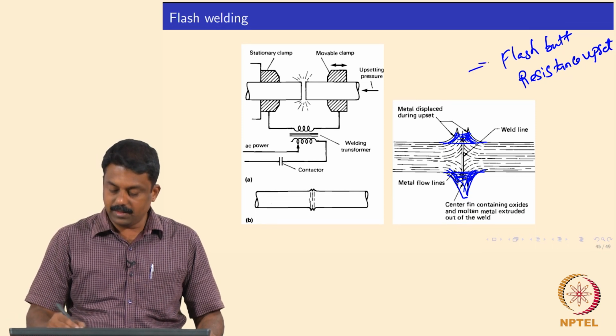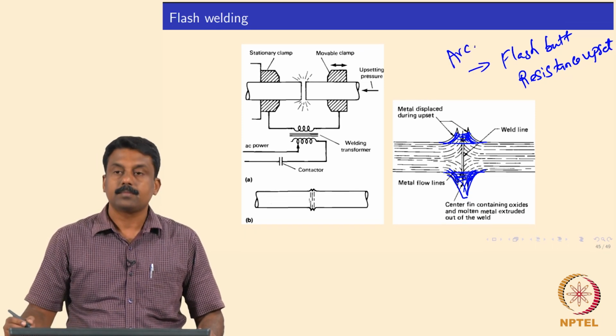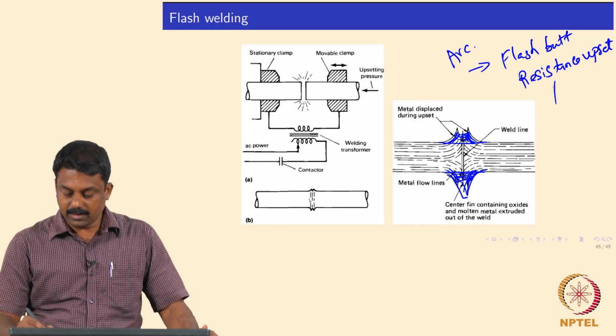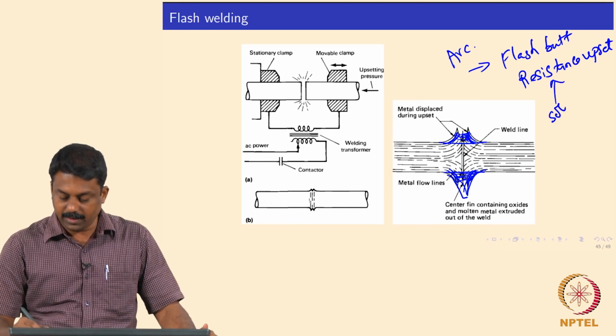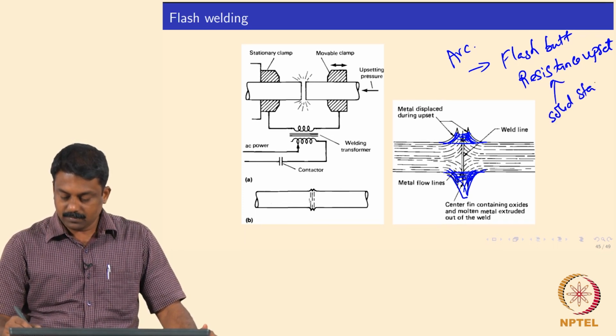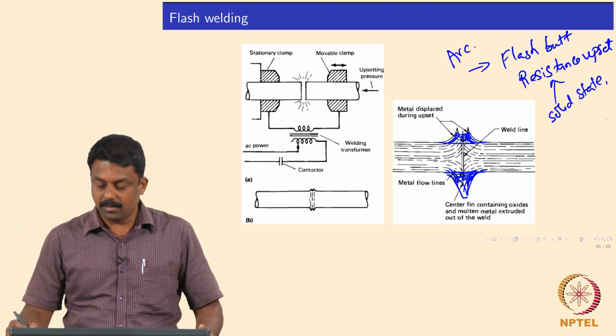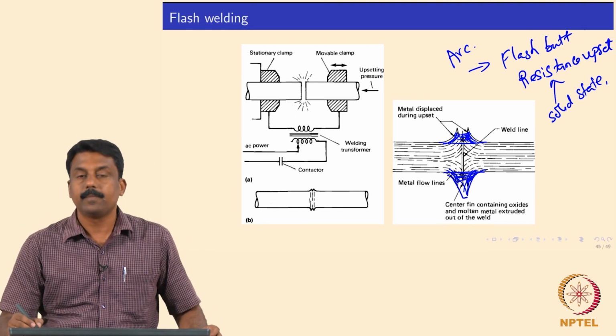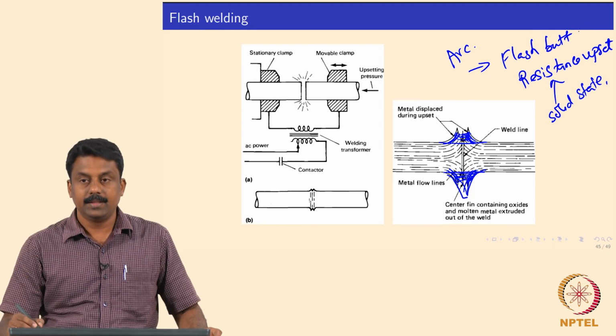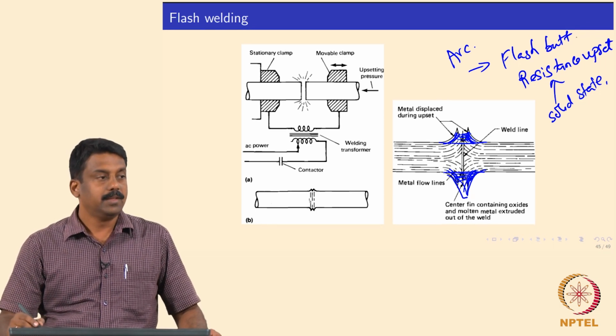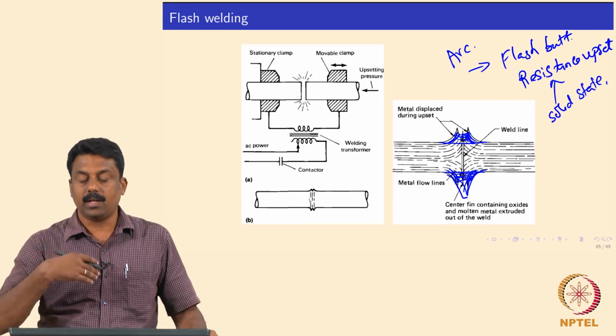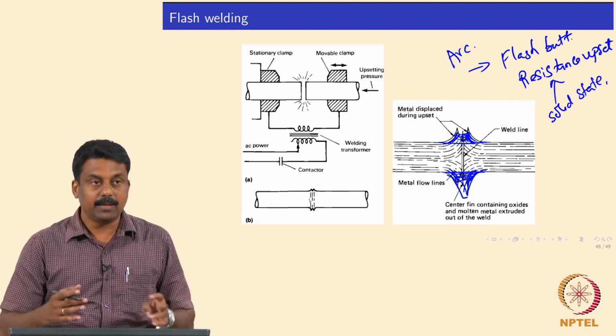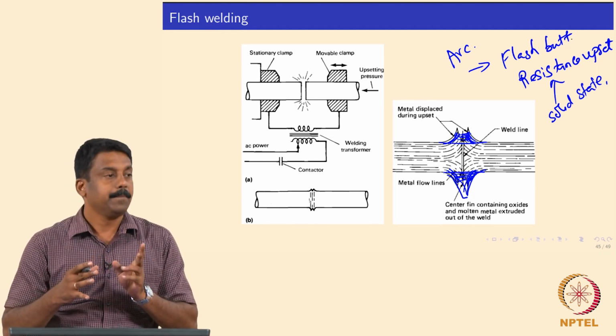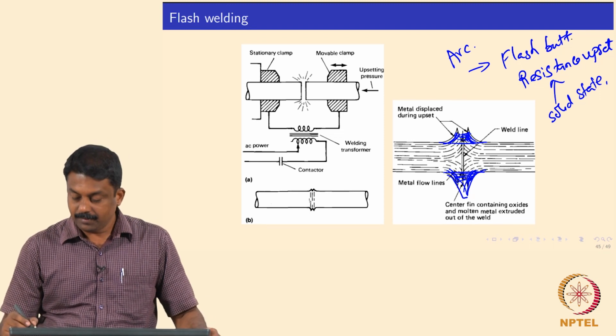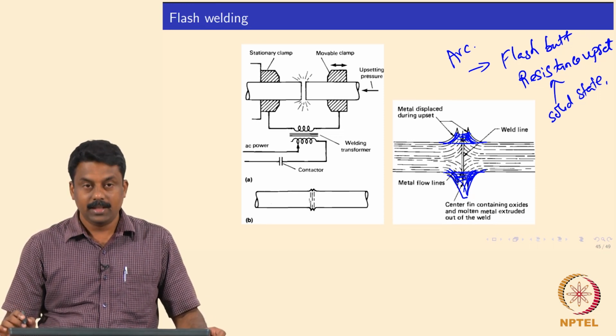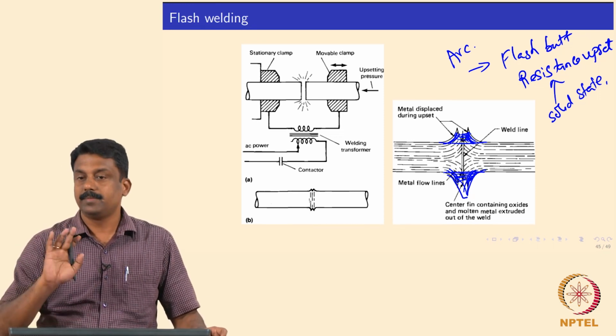Okay, in flash butt welding there is always an arc. Resistance upset is close to solid state welding. In flash butt welding we form an arc, weld the interface and subsequently do upsetting. So the molten interface would be sent out as a flash, and then subsequent mechanical deformation would lead to the joint formation. In resistance upset welding the arcing part is out.